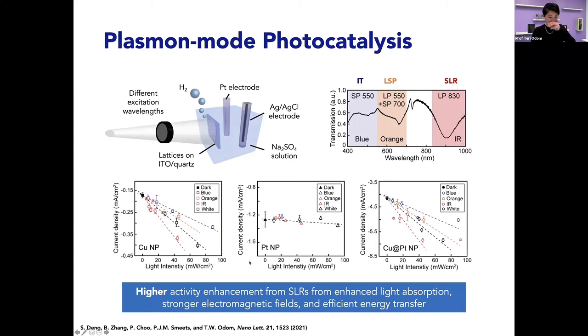And so you can see if we compare these, again, current densities versus the light intensity, and this is just decomposed into where there's no light on, the white light that I showed you in the previous slide, and then these different wavelength comparisons, that there's a more significant increase if we look at these red curves here, which correspond to the SLR. And so it's about two times higher than that from just the localized surface plasmon itself. So there is a distinct advantage to having these SLRs.